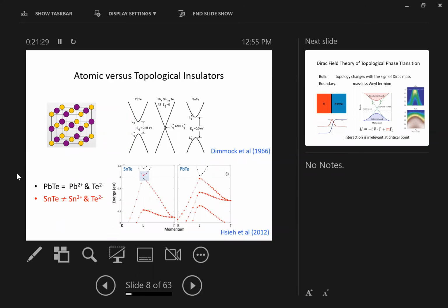Both lead and tin telluride have an energy gap. Okay, so these are all insulating states. But one can actually form an alloy of lead, tin and tellurium. Lead and tin can mix and form an alloy. And as a function of alloy composition, it was experimentally observed that the energy gap initially decreases and then opens up again.